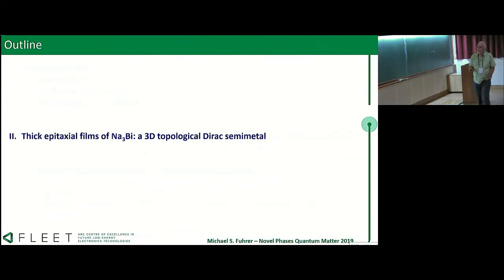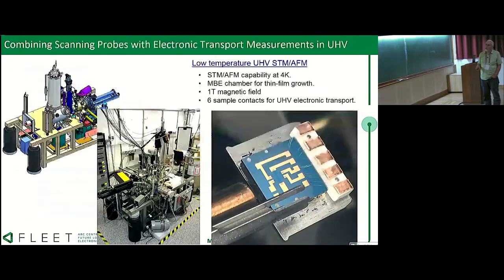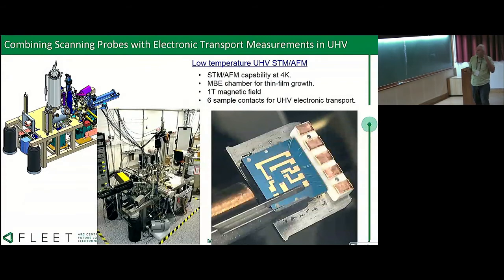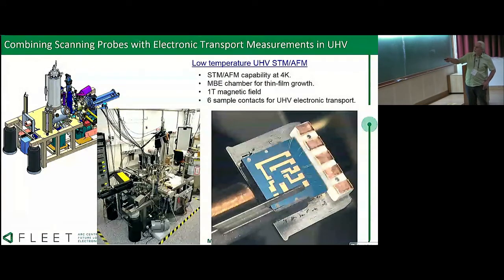I'll talk a little bit about working with thick films of this material. The challenge with sodium-3 bismuth is that it's highly reactive in air. So we do all the experiments in ultra-high vacuum. We have this nifty setup where, it's hard to really see what's going on, there's an MBE chamber here, and a dewar with an STM at the bottom of it. We can grow the material, move it into the cryostat, and do scanning tunneling microscopy, and we can do transport experiments. Our devices look like this, wired up to some electrodes, and we can connect to those wires. We can also put the STM tip right down in the middle of the device and do STM.